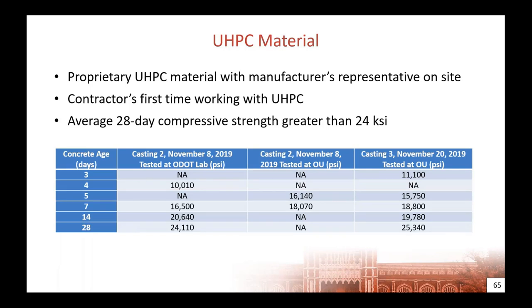The UHPC material that was placed actually met the strengths that we were able to get in the lab, so we had direct comparisons. There was no special curing on these. They were just cast in the field and then taken to either the ODOT lab or the OU lab for compression testing. And our results more or less lined up.